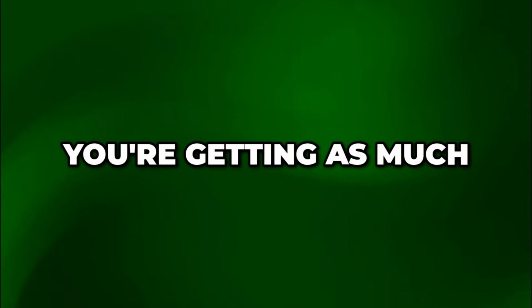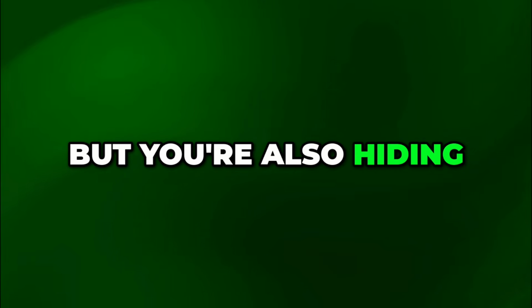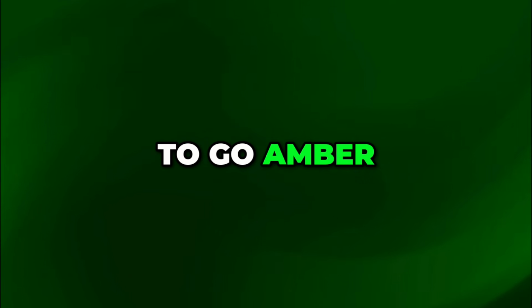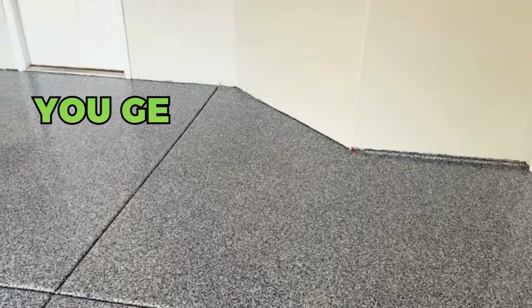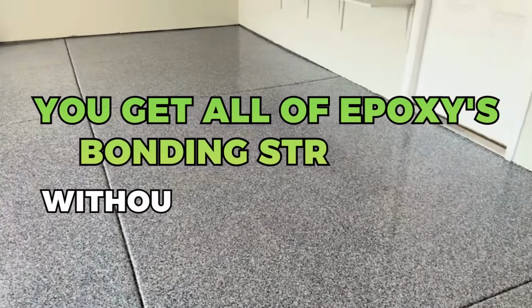Now, here's the really brilliant part that Alex shared. You're getting as much weight and strength into that slab as humanly possible, but you're also hiding the epoxy. That way there's nothing to go amber. So the epoxy never sees the UV because it's under a polyaspartic layer. You get all of the epoxy's bonding strength without the UV weakness.